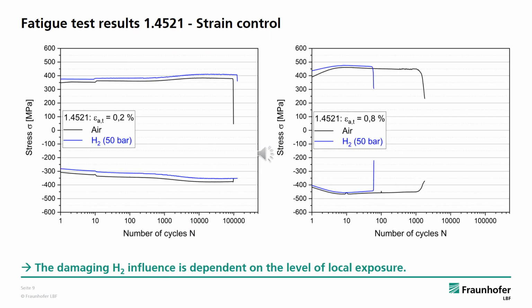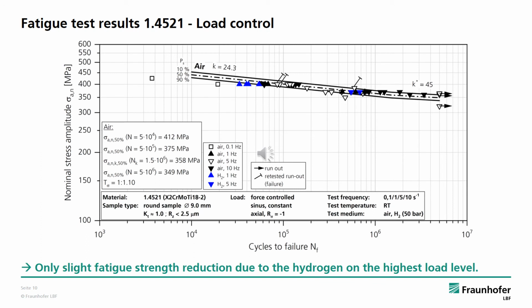This should also be shown in detail on this slide with the application of the stresses depending on the number of cycles. As already mentioned, the life-reducing effect of hydrogen is especially evident at the higher strain horizon of 0.8%. A comparable material behavior can also be observed in the force-controlled tests with the unnotched specimens. The experimental results are plotted in form of SN curves, in black for the tests in air and in blue under hydrogen. The lifetime reducing influence of hydrogen can be observed especially at the highest load horizons.